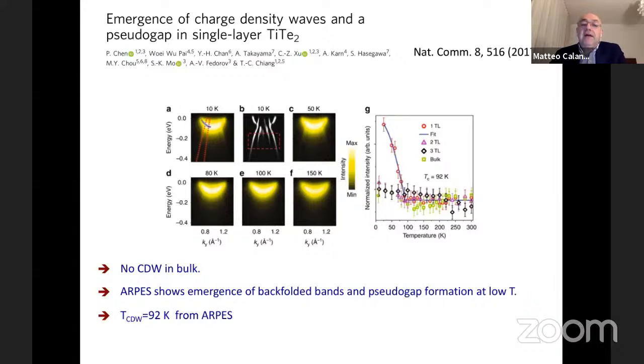However, when you thin titanium ditelluride to single layer, the charge density wave emerges again, and it is the same charge density wave that you see in single-layer titanium diselenide. So this is very surprising, and the charge density wave temperature is much smaller. It's 92 Kelvin from ARPES.